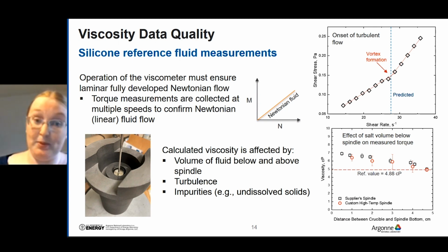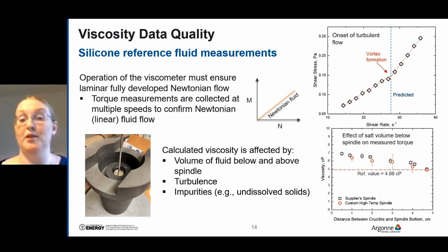Torque measurements are collected at a variety of speeds so that we can confirm that Newtonian flow, that the relationship between M and N is a nice linear relationship. And then we also see that at a particular speed, we will actually get vortex formation starting and that behavior will change. So we can use the relationship of M and N to ensure that we are still in a laminar region.